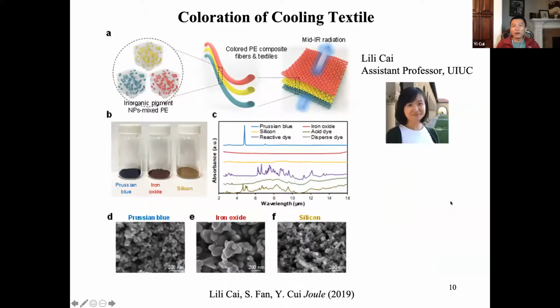But there's one more question we need to pay attention to. This porous textile scatters visible light, the white color. So we cannot get the whole world to wear white, all become white, right? We need to offer different colors. But if you use dye molecules that absorb mid-IR, then your infrared transmittance will not be as good. We have to develop our own inorganic pigment, blended in a small amount into a textile. We measured the mid-infrared transmittance of this pigment, and it's great. They don't absorb.